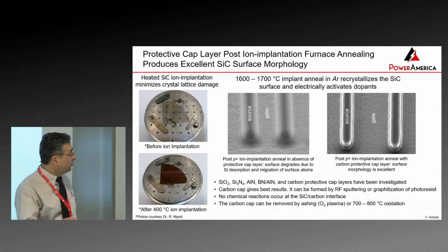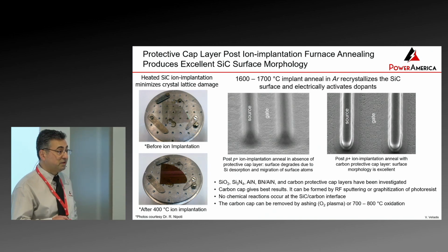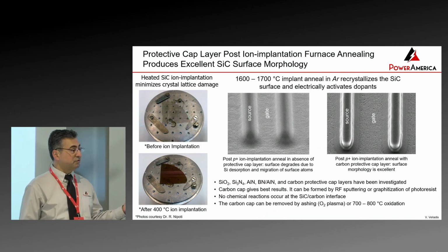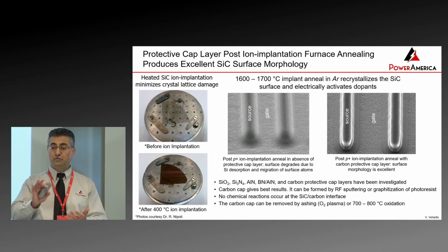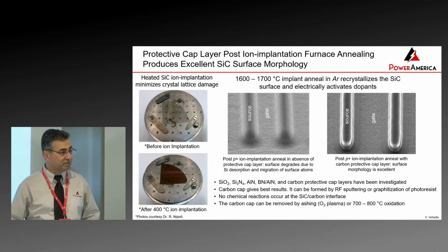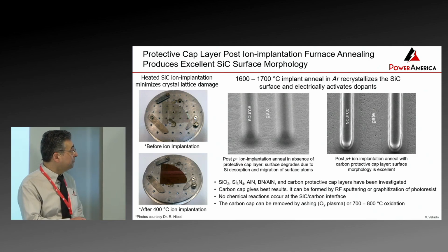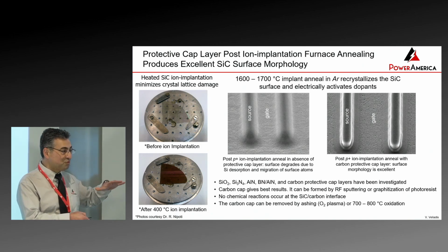Now, you need to put a special coating to do this right. This wafer did not receive a coating. I gave it to my technician. I gave him the recipe for the coating. Instead of putting it on the front of the wafer, he put it on the back. Didn't work that well. But at the same time, some wafers from that same lot got the coating where it needed to be.